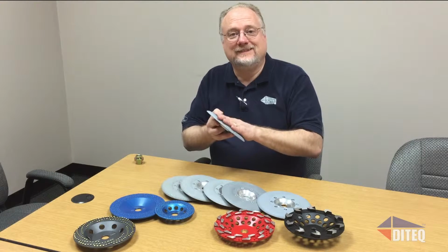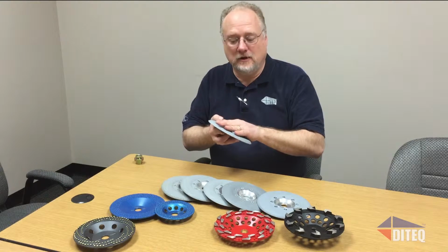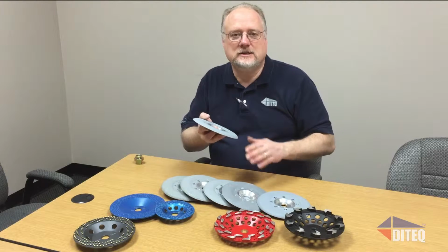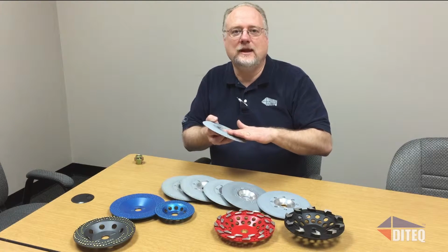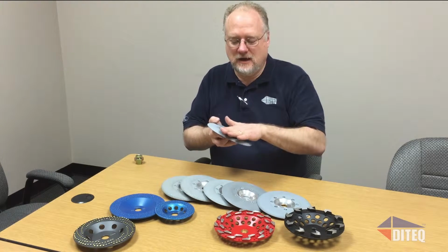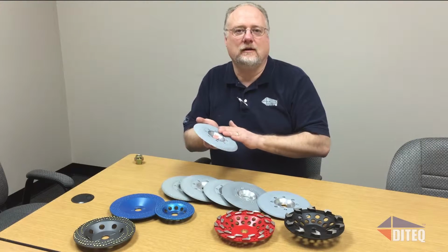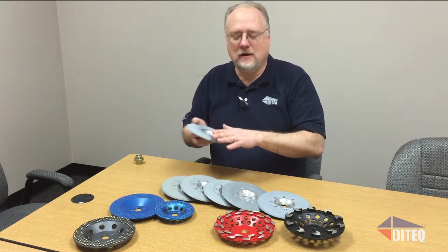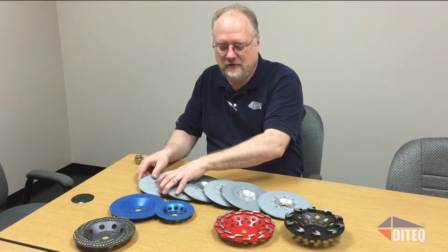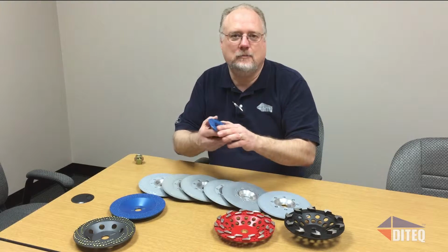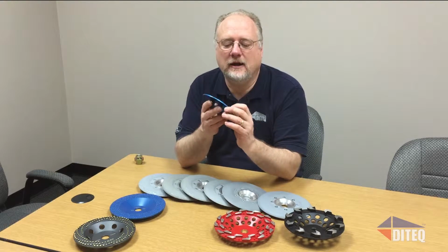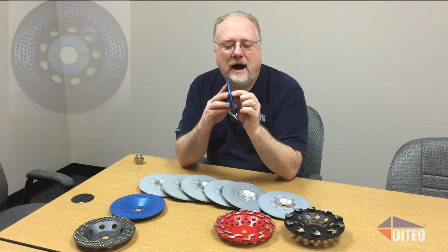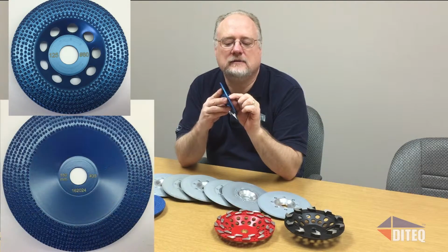The problem with a single layer vacuum brazed cup wheel is if you're removing a lot of material, the material can get between the diamond crystals and it'll be smooth, so it won't work. It'll be plugged up. You'll plug up the diamonds in essence. So that's why we came out with a spike cup wheel. These are vacuum brazed little piles of smaller diamonds.